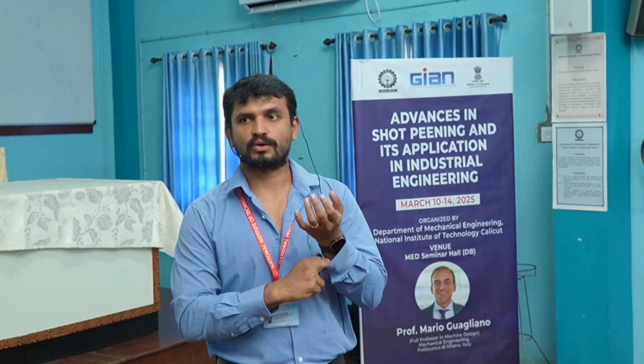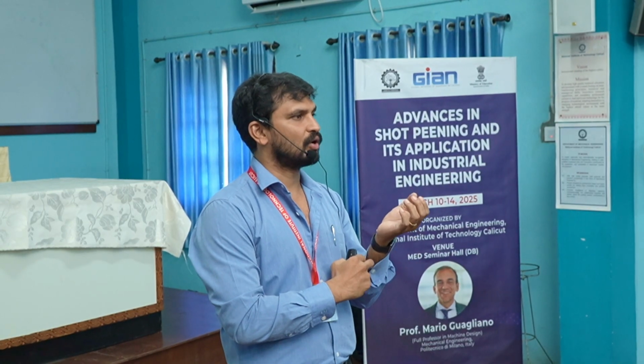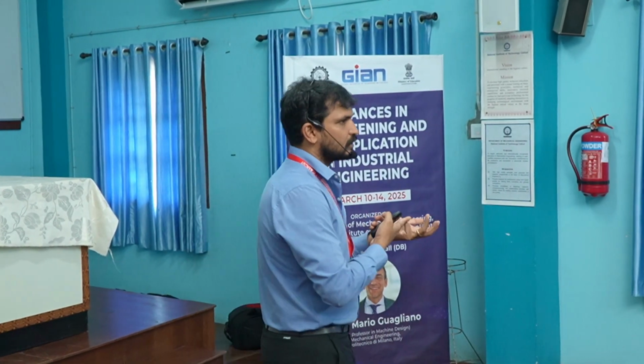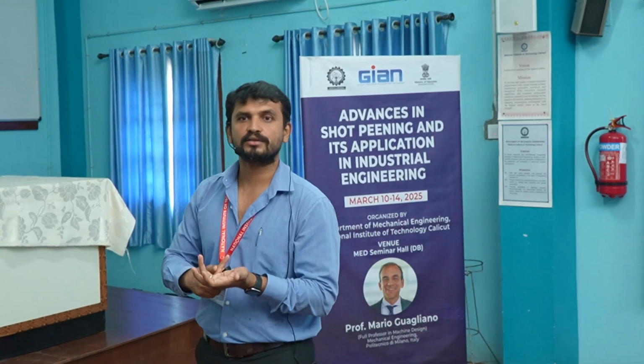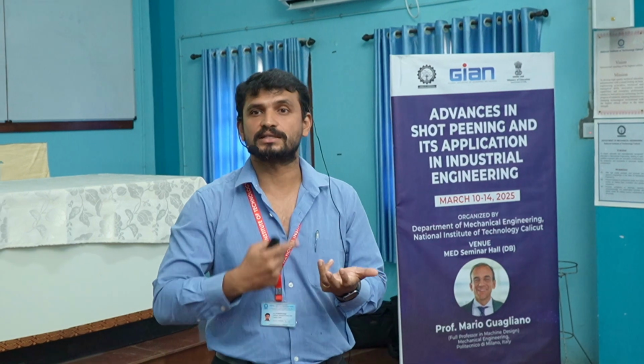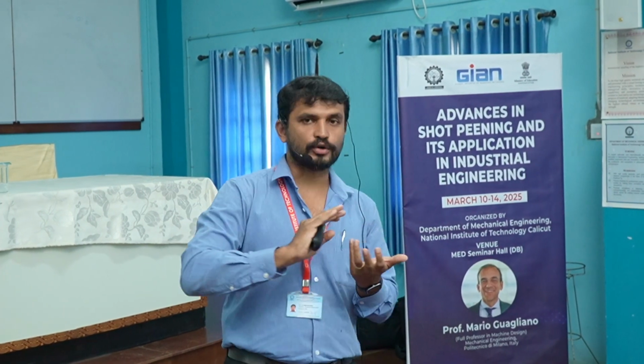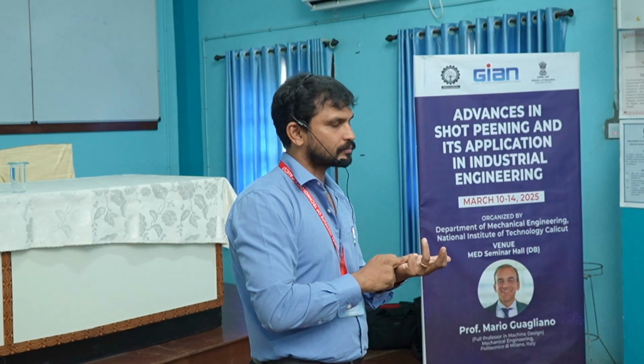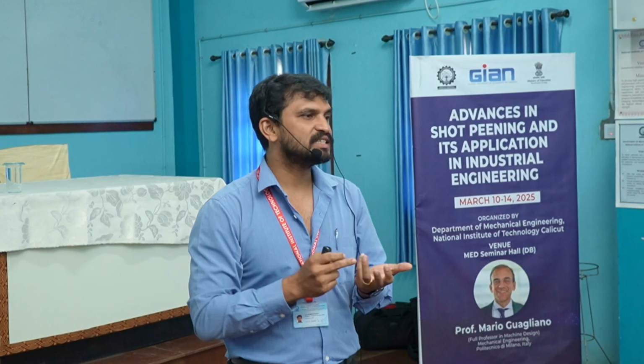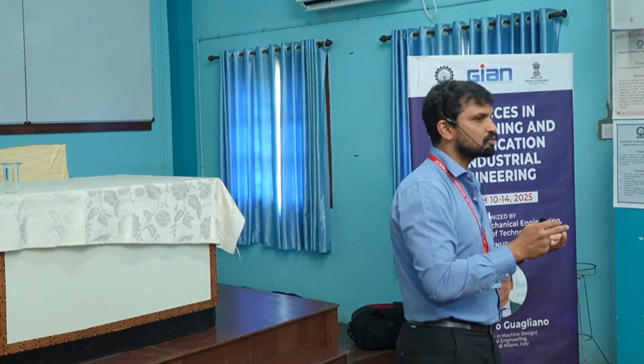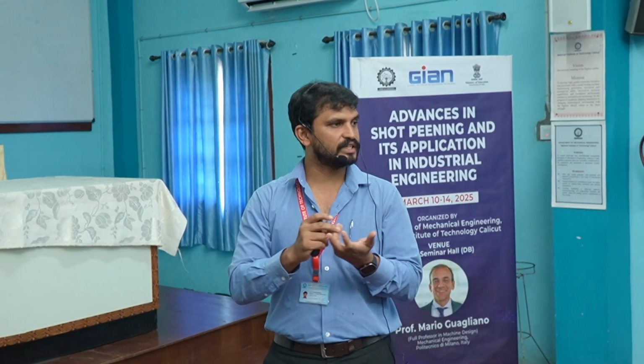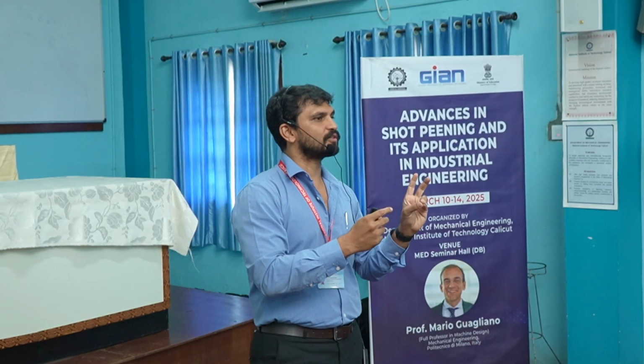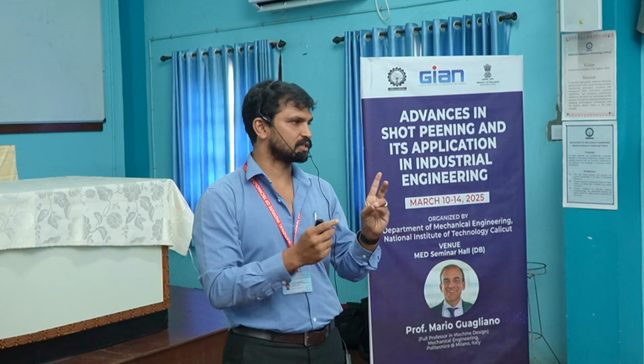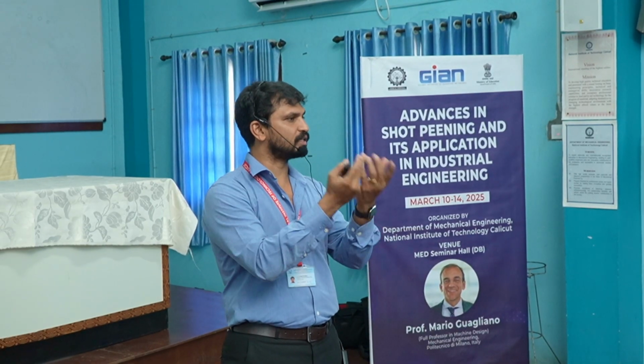And with this, I would like to wind up. In order to overcome the residual stresses or these kinds of defects, I told you there are two major reasons. One is the fatigue strength, which is comparatively lower for additively manufactured components, and also it is inconsistent. So in order to improve that, we are using shot peening. Also to change the tensile residual stresses formed on the surfaces to compressive residual stresses, and also to improve the surface properties or surface roughness, we require shot peening.